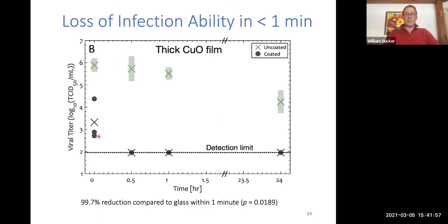Even at 0 minutes, which is basically Alex, our collaborator, just putting the droplet on and then pulling it off, which was probably about 10 seconds, it wiped out nearly three orders of magnitude. So we were down to 99.5% inactivation in seconds. That's fantastic, or 99.7% reduction in that 1 minute.